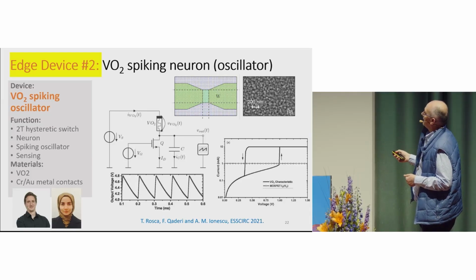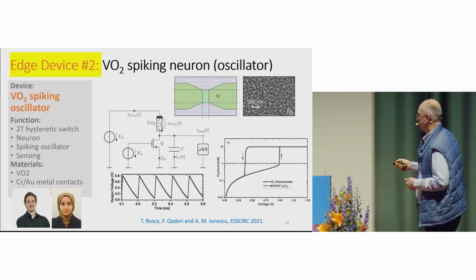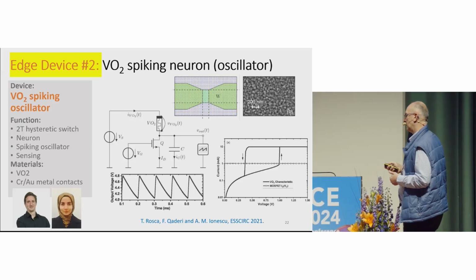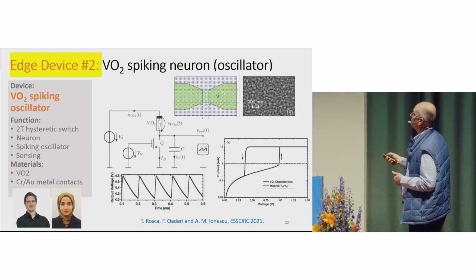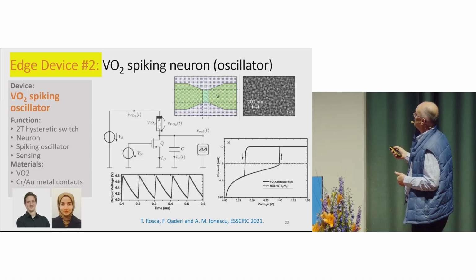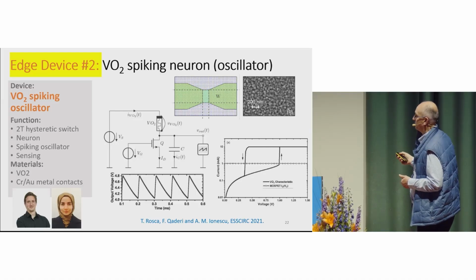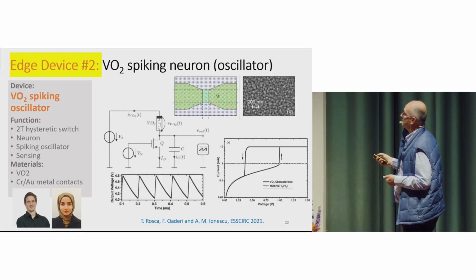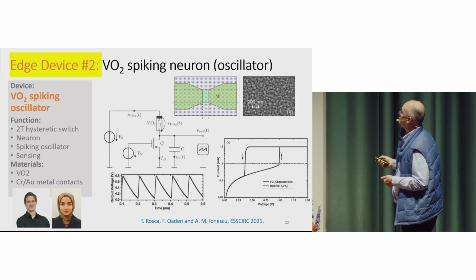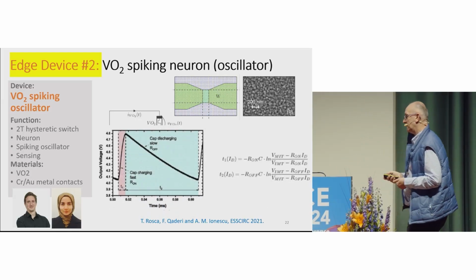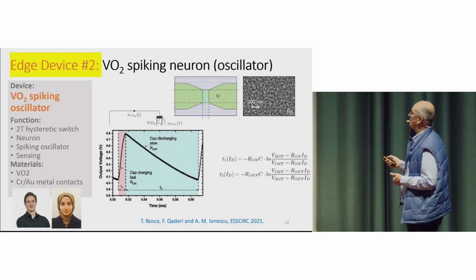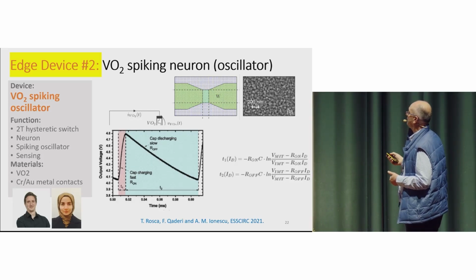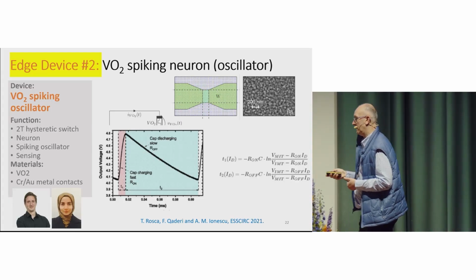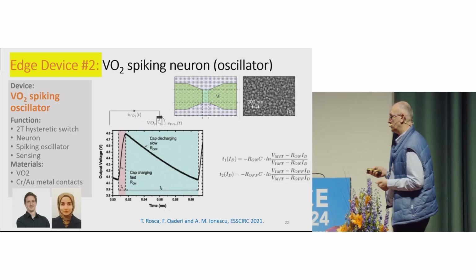But you see, now the operation point is a very simple, basic electronics exercise: to find the operation point of this is the intersection of this curve, and then you have two unstable points. So this is an unstable oscillator that, if you fine-tune it with a capacitor at the output, will generate a train of spikes. The nice thing is that you can generate this train of spikes and shape it according to the parameters of your material, the R on, R off, the level of MIT and IMT transition. So you can design the spike as you wish, or you can tune it with the voltage that you apply